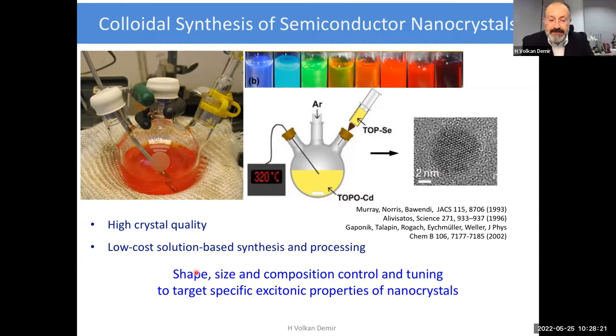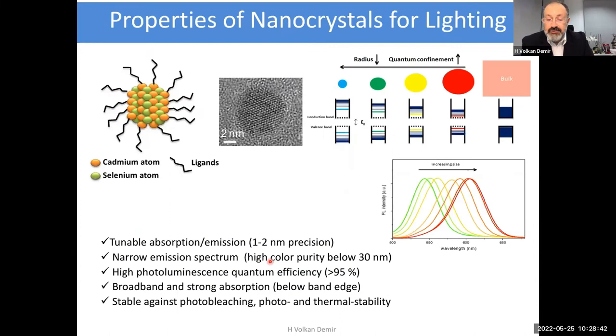And in this synthesis, we can get shape, size, composition, well-controlled, well-tuned, and we can target specific exciton properties. And I'm very pleased to acknowledge some of the pioneering groups over the years that indeed helped to shape nanocrystals that we can achieve very routinely in our labs today. And in our lab today, we can actually hit the peak emission wavelength within 1 to 2 nanometer precision each time. This is, to me, a great level of reproducibility.